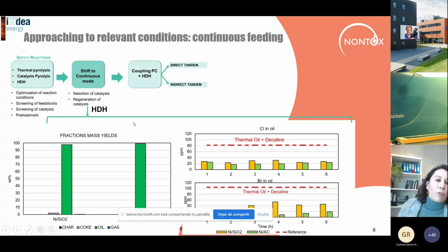The same was carried out for the HDH reaction. We evaluated different catalysts, two catalysts, nickel supported onto silica and onto activated carbon, during 6 hours. And in this case, it was the nickel supported on activated carbon, the one exhibiting the best performance in terms of stability during the reaction and in terms of halogen contents, which was very low, below 20 and even 10 ppm in the oil.